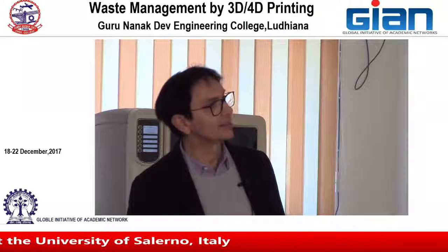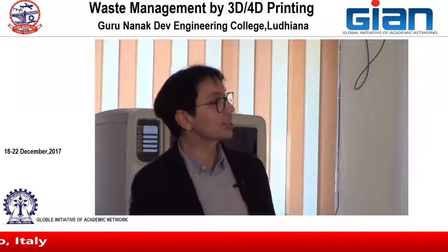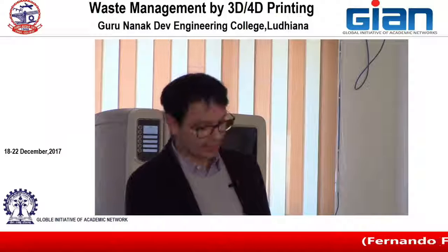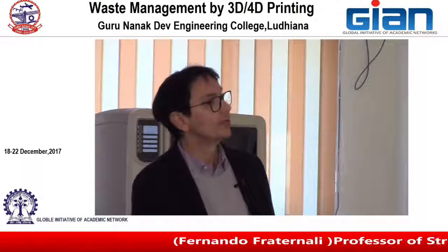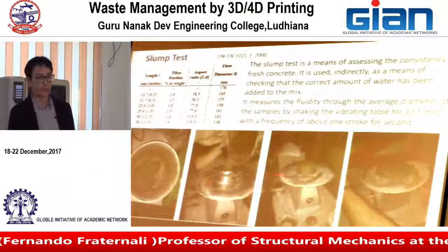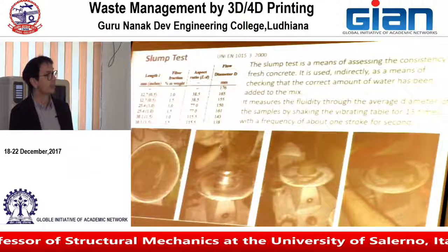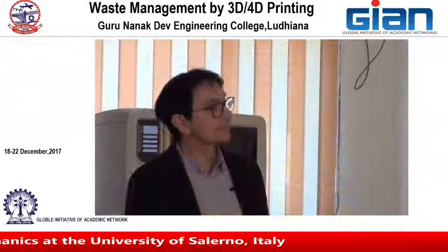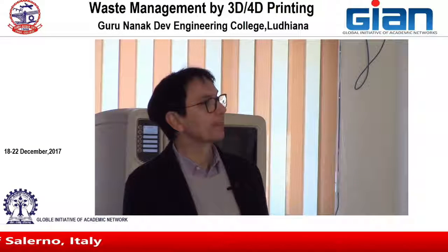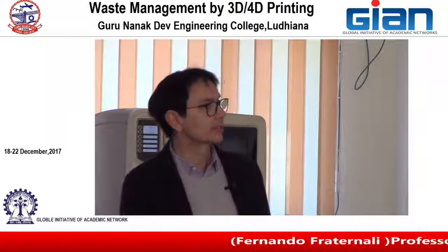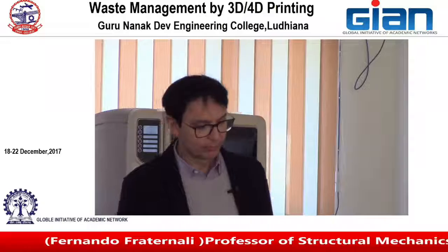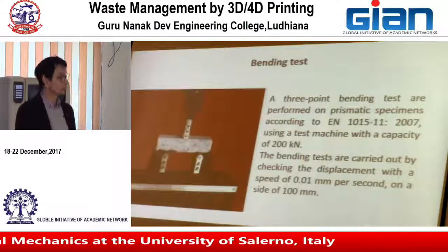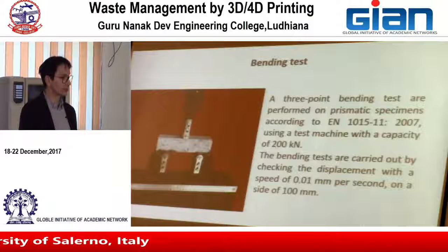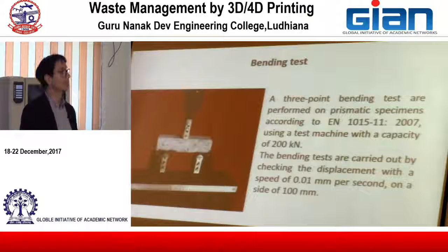And this is the mixing process. This is the slump test, which shows you the fluidity of the material after mixing. And the results were good, pretty acceptable. In the bending test, 3 point in this case on these smaller size specimens of mortars,